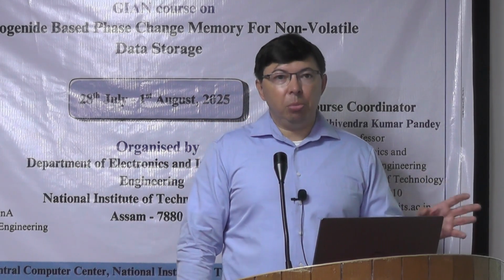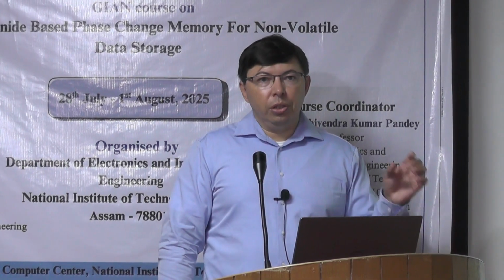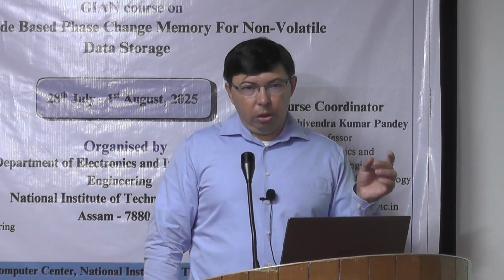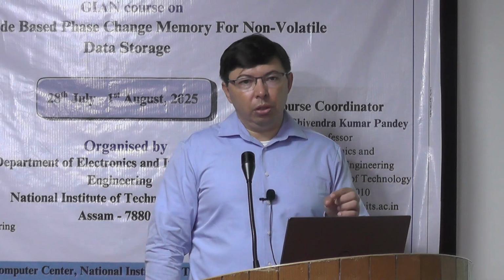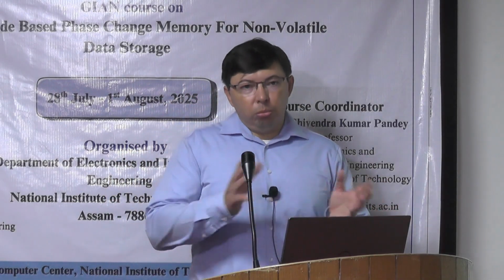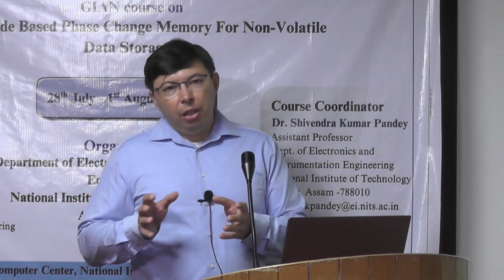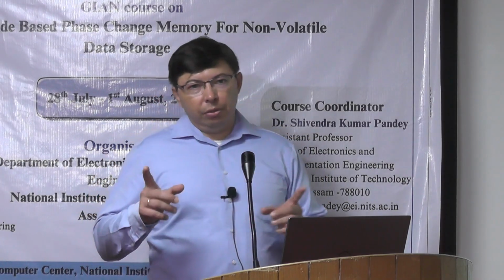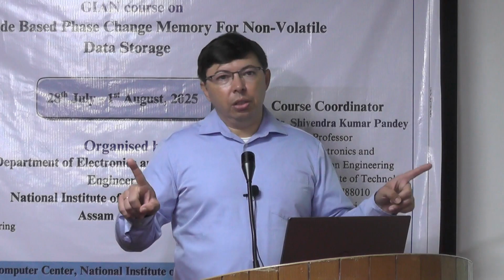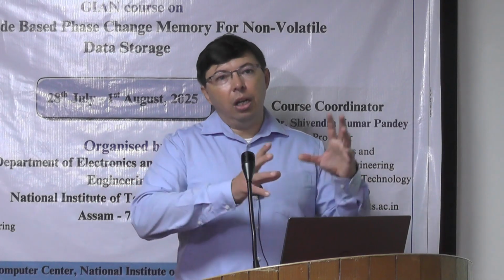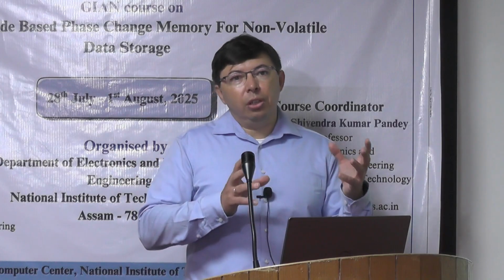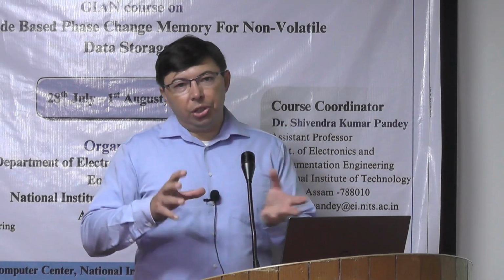You need to first make the experimental data, measure it. You should know the distances in your experimental setup, and then you put them into the Monte Carlo simulations, and the simulations give you a structure. Then you calculate the RDF again, then you adjust the structure. This is iterative, to fit the experimental and simulated data, until you have a nice fit. You can say, yeah, it could be my structure, but you can create different structures which can fit this RDF. So we are going to run a lot of iterations.